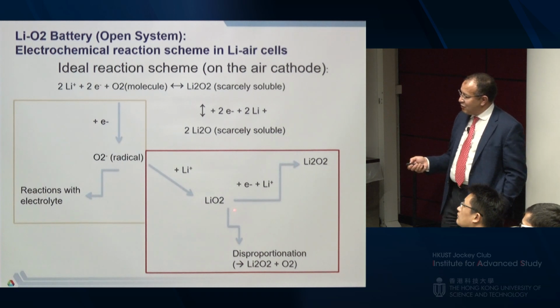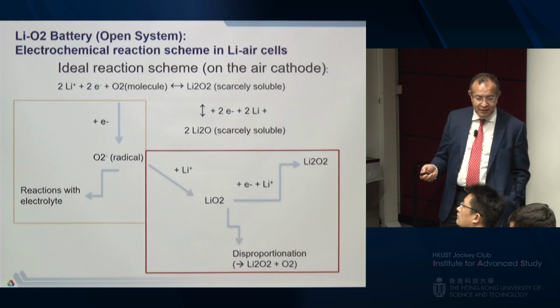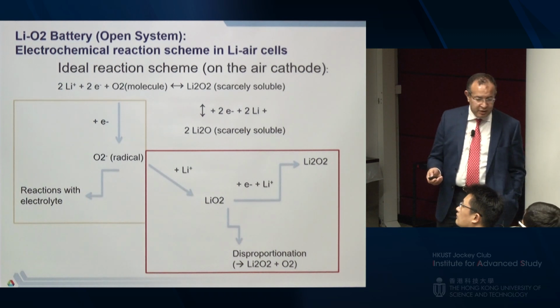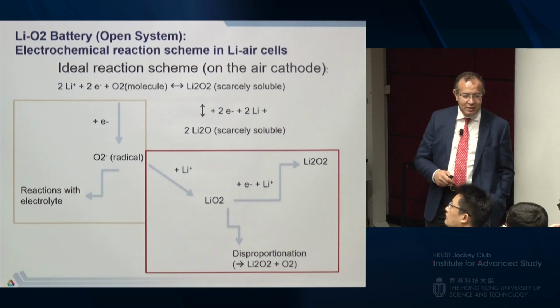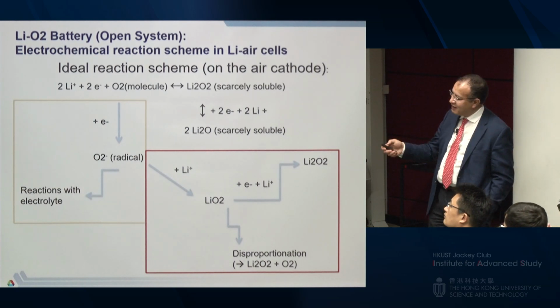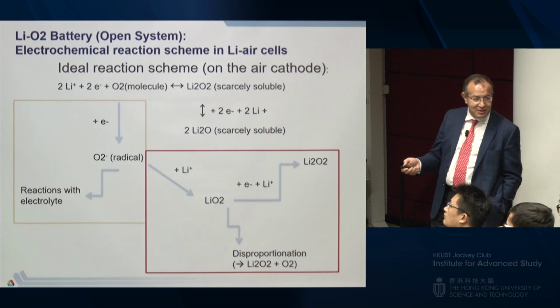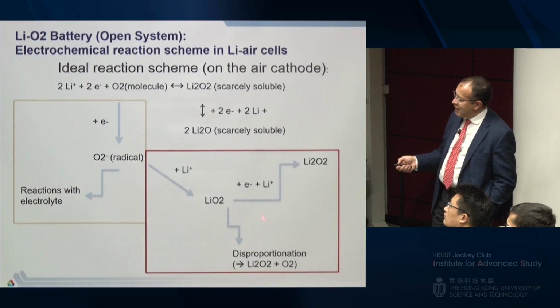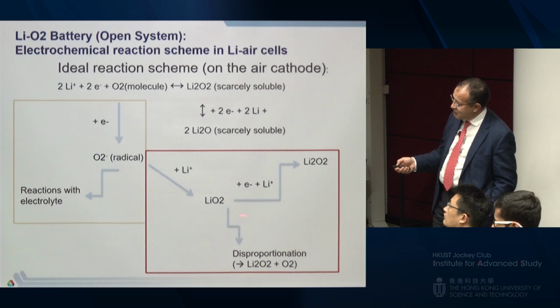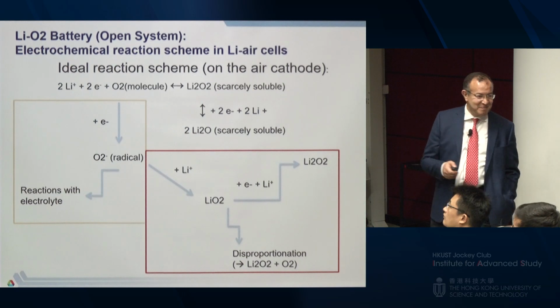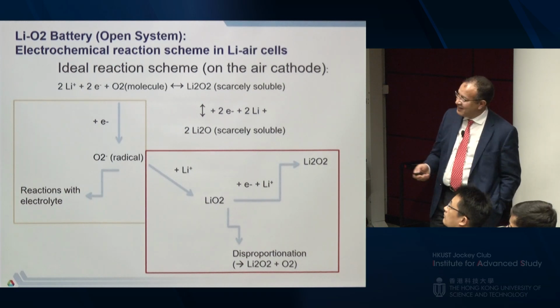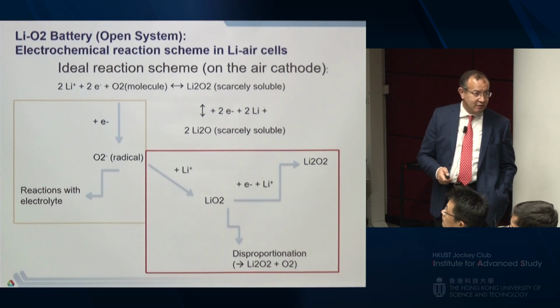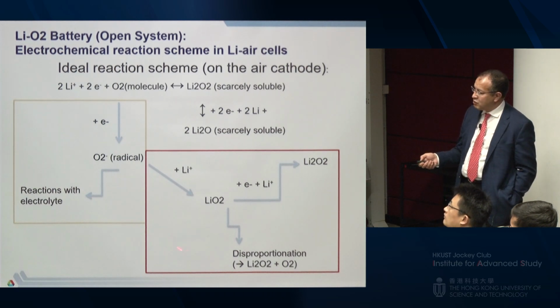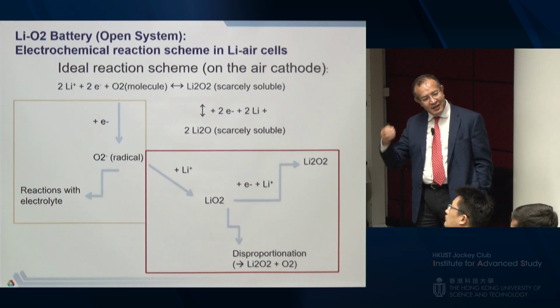The problem is, if you look at the literature, and it's true, if you form an amorphous lithium superoxide, amorphous lithium superoxide disproportionates almost immediately, within a second, and you form lithium peroxide and you release oxygen. But what happens if you stabilize this system and go this way? You notice here there is no oxygen. That's a closed system, like lithium-ion. And the energy out of this system is very, very high. Because in the lithium air, we still need a tank of oxygen. That's a hit in energy right there.